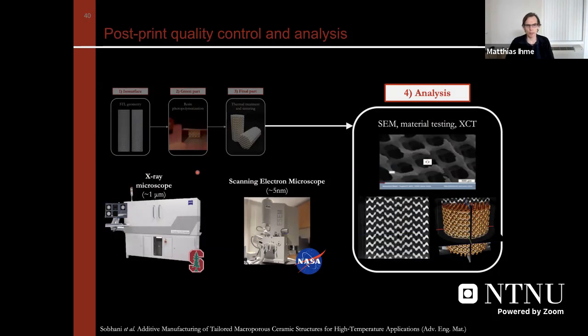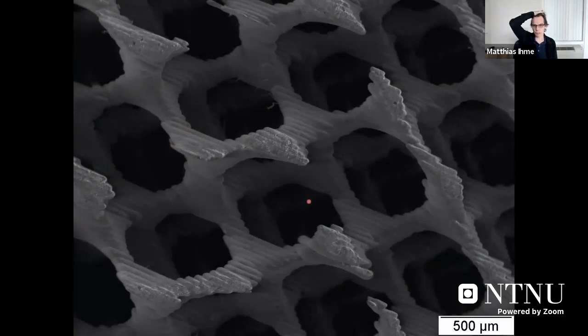So in total, we have the manufacturing process. We did the analysis, and I want to show you some of the results where we employed SEM and an X-ray tomography system to look at the pore structure and the material stability during the combustion process. The first result that I want to show you is an SEM image of these pore structures. You're looking right inside the structures. The scale is about 500 micrometers, and you're clearly seeing the formation of the pore topology, the layer material here, where we're essentially using this sintering process with these very fine structures.